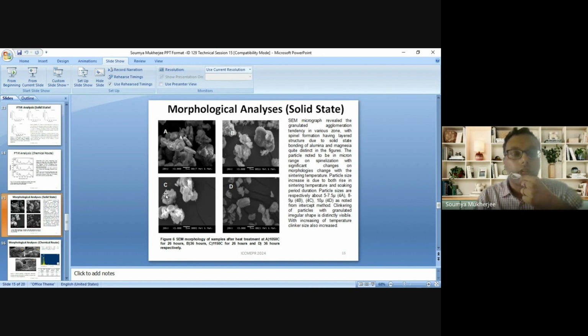Now, more focus on the morphological analysis. From the solid state process, we are getting some cuboid structure in some places with an agglomeration tendency, but there are no interconnected cracks in general, and the sizes are in the micron range, 5 to 7 micron, 8 to 9 micron, and close to 10 micron if we vary the durations and the heat treatment temperature.